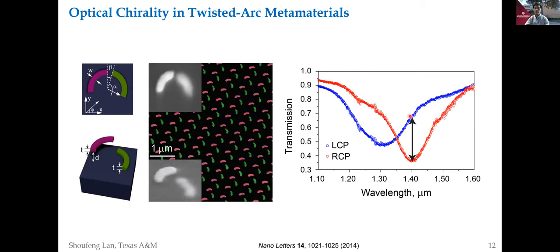And we found that rather than several pitches, half of a pitch is already good enough. We further separate the half pitch into two arcs with an angle beta. And we place those two arcs into two layers. This action dramatically reduced the fabrication burden because now we can fabricate it layer by layer, while this action will not sacrifice the chirality.